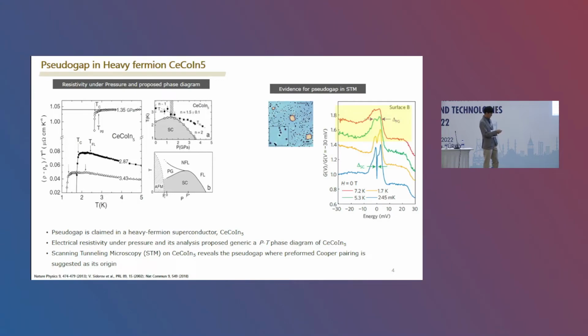In STS measurements, there was also evidence. For example, this is the differential conductance versus bias voltage. At base temperature, around 245 millikelvin, there is a sharp suppression due to the superconducting energy gap, and there is an additional feature at a wider energy range. When you increase the temperature to 1.7 Kelvin, then 5.3 Kelvin, even 7.2 Kelvin, which is higher than Tc of 2.3 Kelvin, you can still see that even though the superconducting feature disappeared, a gap-like feature survives. So they attribute it to a pseudogap.